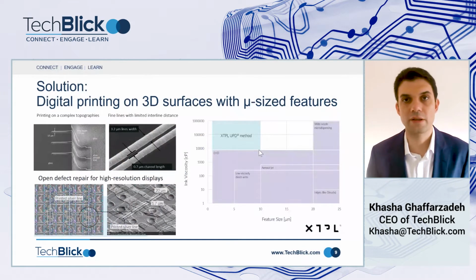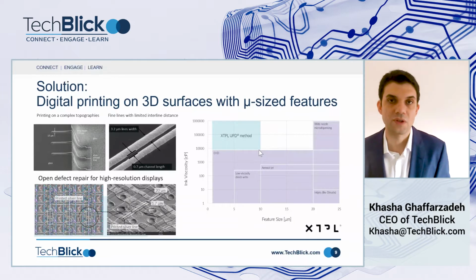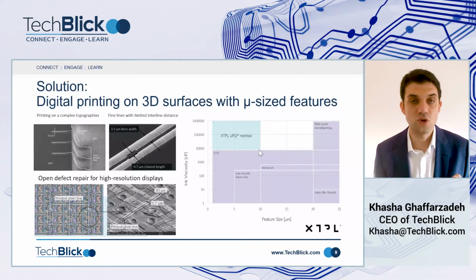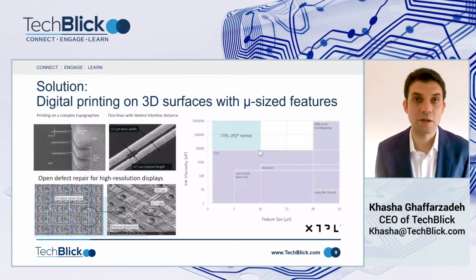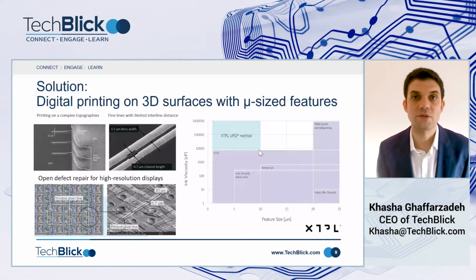And again, here I want to highlight this very interesting company, XTPL, out of Poland. And what they do is they have a digital printer that can achieve, using their own viscous silver nanoparticle inks, very fine lines. So here on the top left-hand side, you can see examples where they've printed, let's say, a 3.2 micrometer line with a spacing of just 0.7 micrometers. And if you look at the bottom left-hand side, you can see examples of this technology being applied to create open defect repair in high resolution displays. Of course, this could be applied to MicroLEDs, but also other types of displays.